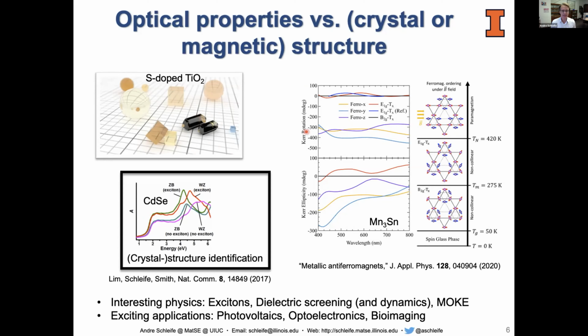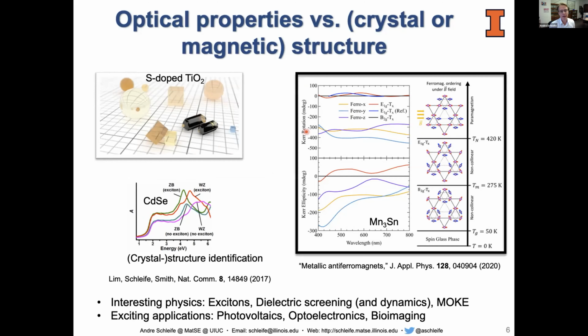And then the second example is we did a similar study for magnetic ordering, in this case of a material, manganese 3 tin, which you can sort of see on the right hand side here can appear in various magnetic orderings, but at very low temperatures, apparently the people report a spin glass phase. That sounds complicated, and it is complicated for simulations.